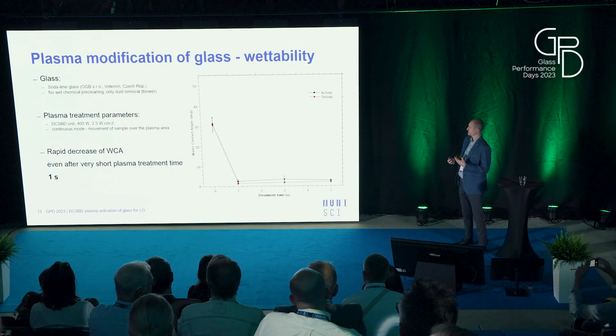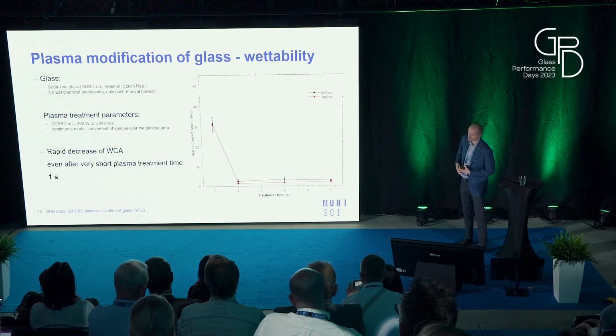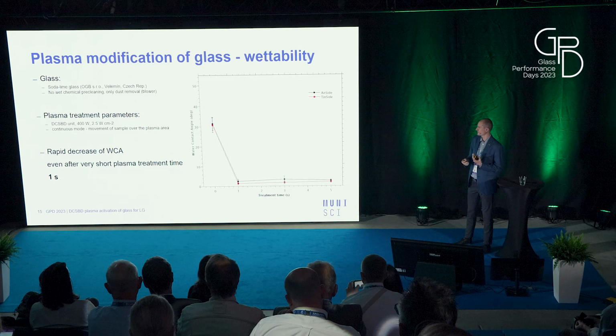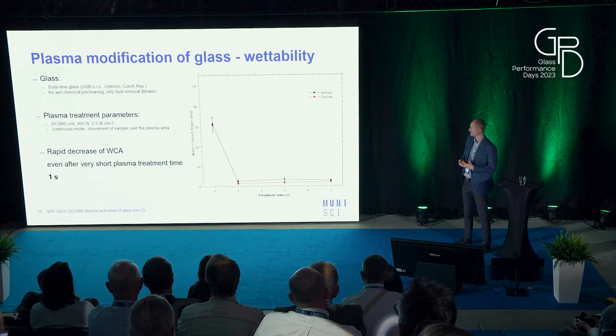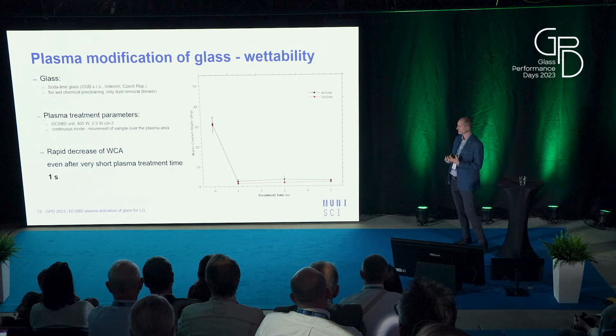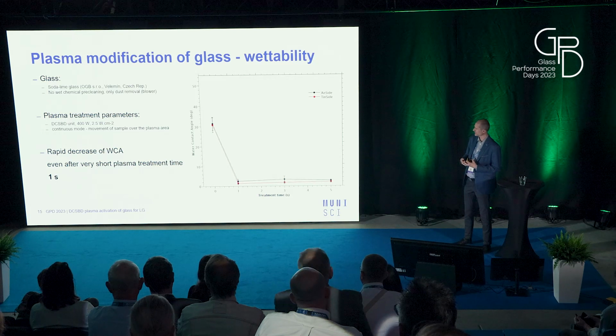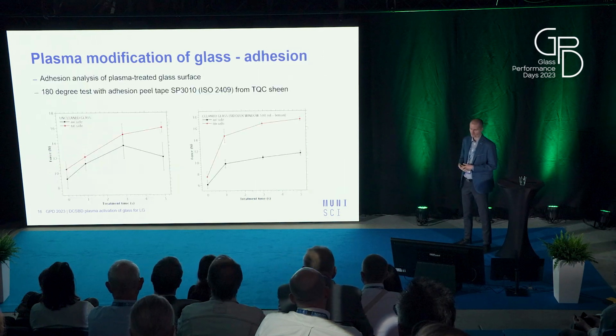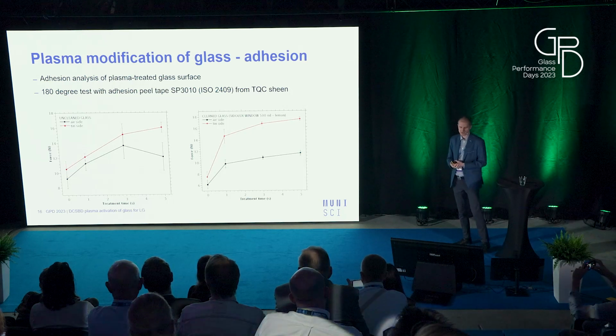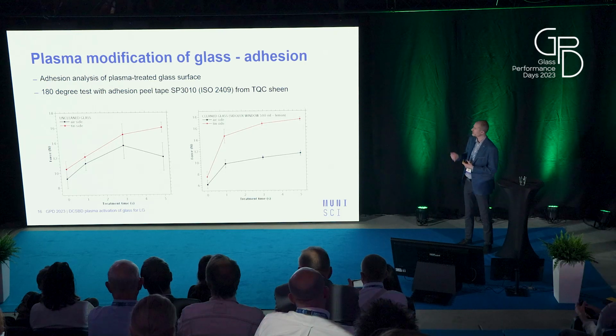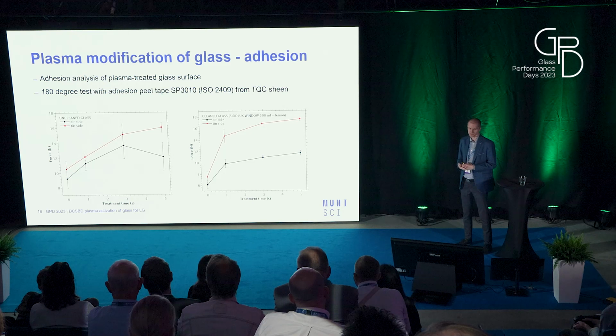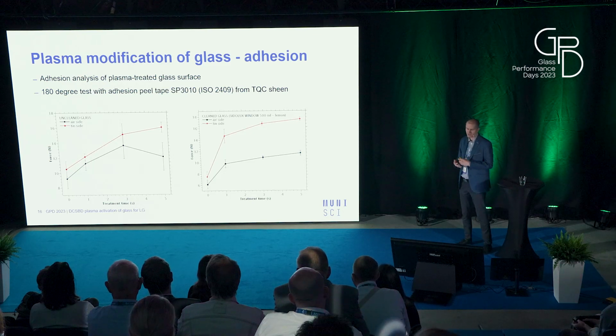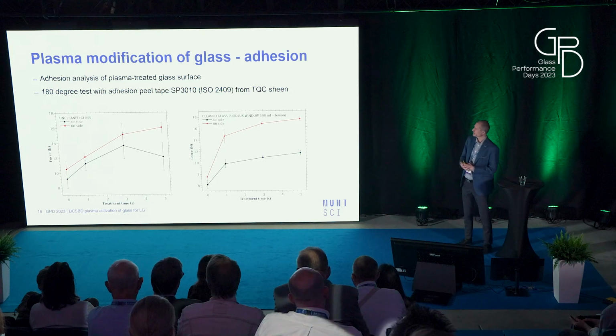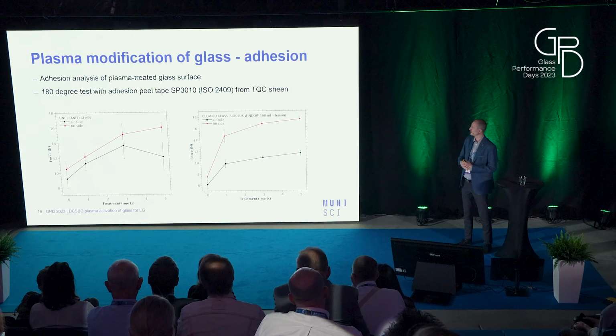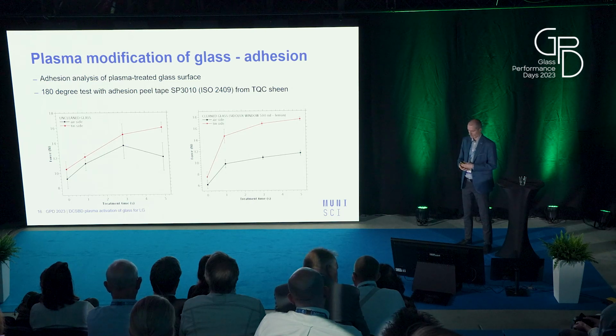If we apply the plasma on the surface of glass, we can see a very rapid decrease of water contact angle. Water contact angle is a value which can assess the wettability of the surface. We can see that even after 1 second, very fast treatment, there is a very sharp decrease of this water contact angle. We can also measure the adhesion of the plasma treated glass, and as you can see in these two graphs, one of them is for as received glass, and one of them is for pre-cleaned glass. We can see an increase of adhesion properties. This was measured by a standard adhesion peel test using this ISO test.